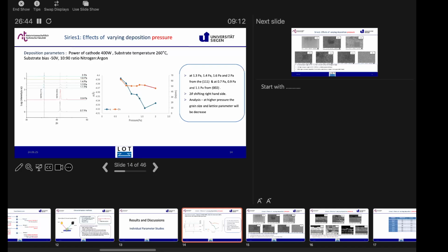This was deposited on copper, and this is a copper reflection, and for copper it should be more or less the same. And this 200 is really highly intense. I even tried pole figures from such samples, and it was really oriented into 200. And this is log scale.